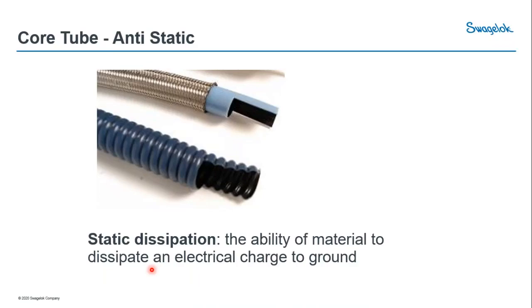Static dissipation. Basically, if you have a line or a hose and you use a standard Teflon core, not carbon black, that means the hose is not grounded. So you could have, say, steam or a polymer going through that at a high velocity that may create a static. The spark will take the path of least resistance and actually go right through the side of the hose, and that would cause maybe a leak or a failure.